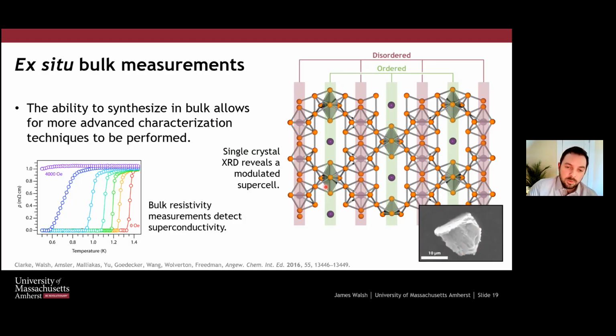And so that means that we have channels of disordered copper-5 moieties, which can coexist in the model with bismuth atoms. And then we have channels of ordered copper-5 moieties and bismuth atoms. And so that's really interesting. So this was work done by Samantha Clark, now at Lawrence Livermore. She's an excellent crystallographer and was able to solve this crystal structure. But again, we would not be able to see this kind of complexity just using the diamond cell data.